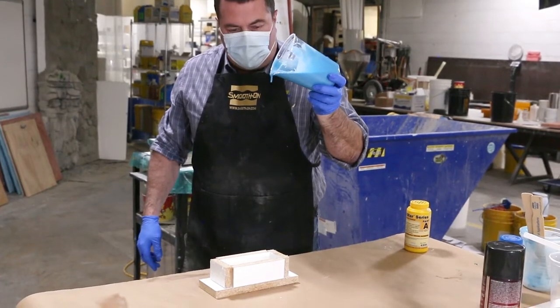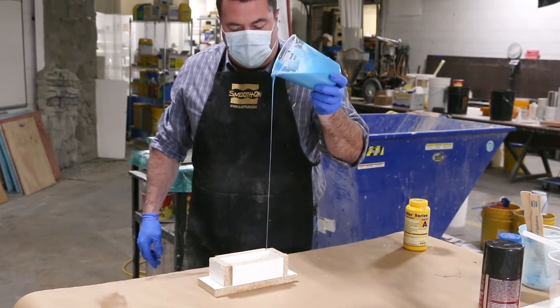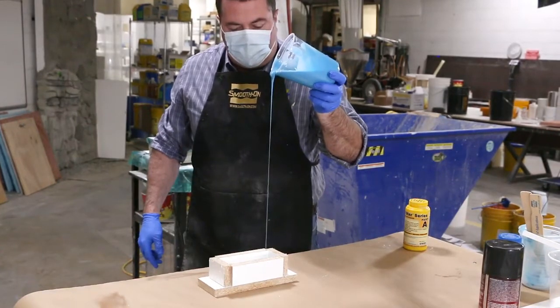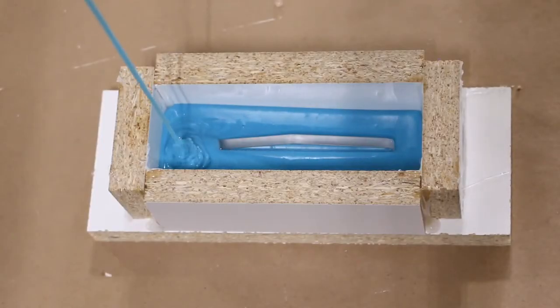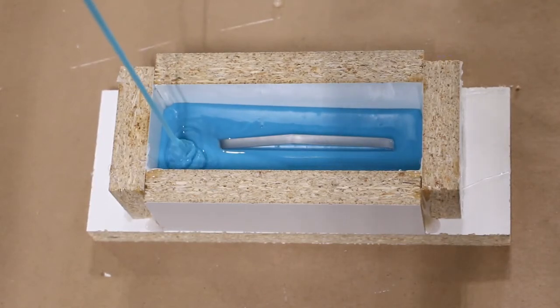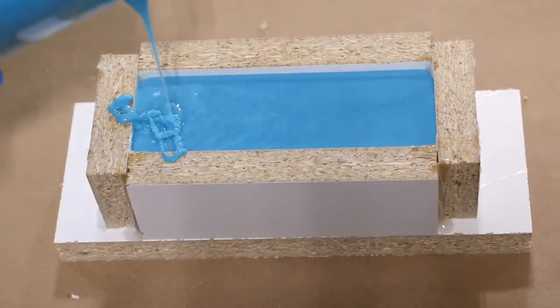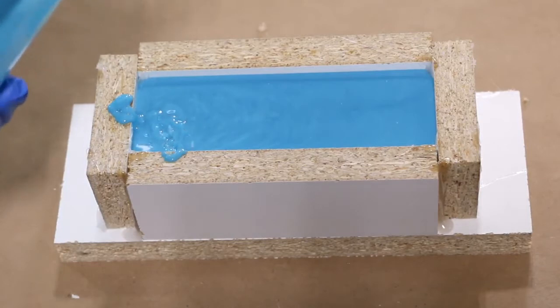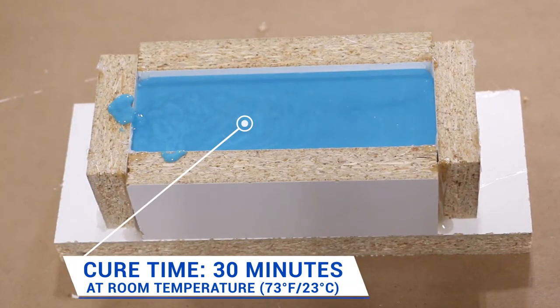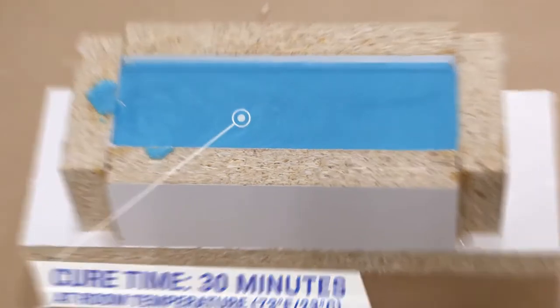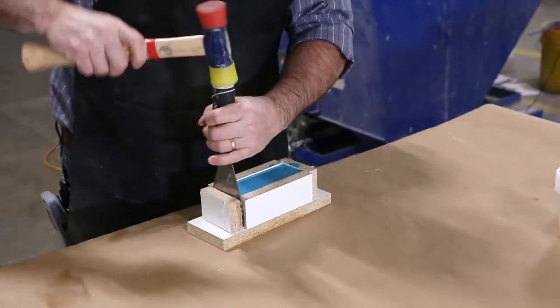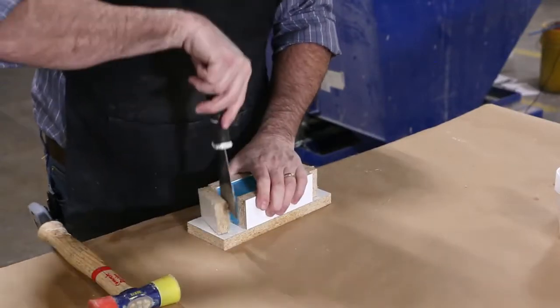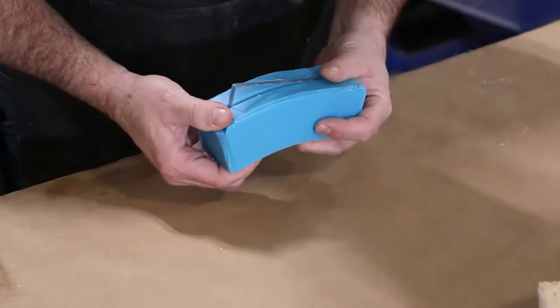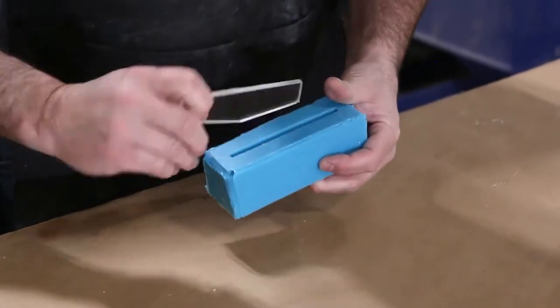Pour the material in a high stream to allow any air bubbles to be released. Fill the mold box until the model is covered by at least a 1/2 inch over the highest point. Allow the rubber to cure for at least 30 minutes. Once cured, remove the sides to release the mold. Remove the acrylic model and prepare to cast the slot plug for the sink.